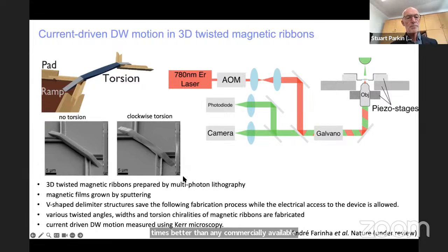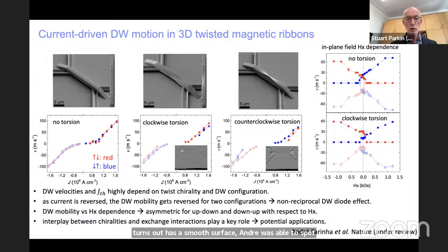And so, as you can see in these photographs or SEMs of the structures that Andre has built, we build structures which are like little bridges, if you like, with flat surfaces, no torsion, or where the surface has a torsion twisting to the right and then twisting to the left. And then on top of this polymerized structure, which turns out has a smooth surface, Andre was able to sputter deposit the racetrack materials and then observe the motion of domain walls. And what you find then is that depending upon whether you have torsion or whether the torsion is clockwise or anti-clockwise, then a sequence of domain walls with up, down, which are red, and down, up, blue, will move at different velocities. And it turns out this is due to the geometrical torsion that we've introduced and its impact on the chiral domain wall. So this is a very nice demonstration of the interaction of spatial and spin chiralities. We're still working on getting this published.